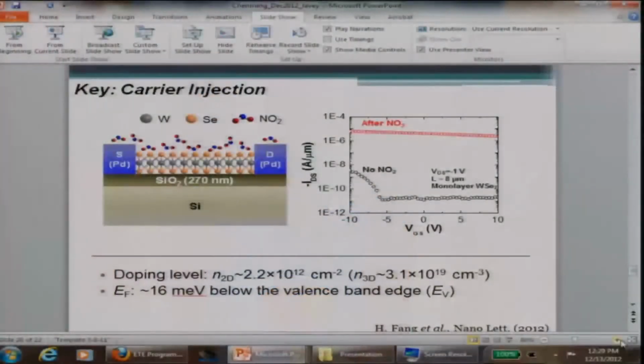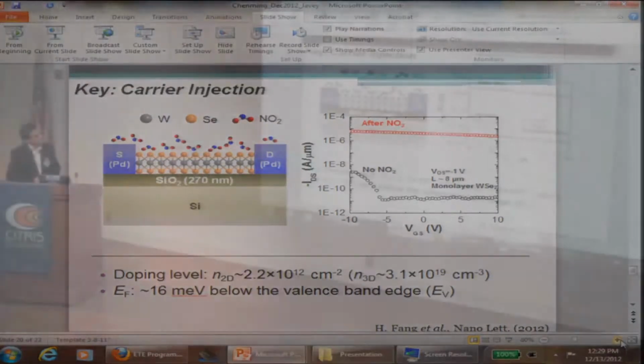We still have some Schottky barriers with palladium. How do we deal with it? In silicon, we know that you have to dope your contacts, the region underneath the metal contact. You want them to be as heavily doped as possible to make the Schottky barriers as thin as possible. So here, how do you dope? Do you start replacing the atoms? And if so, wouldn't that introduce defects? What would be the right doping approach?